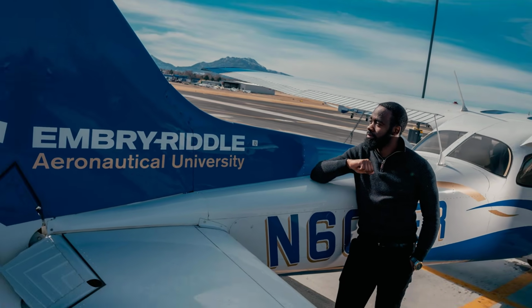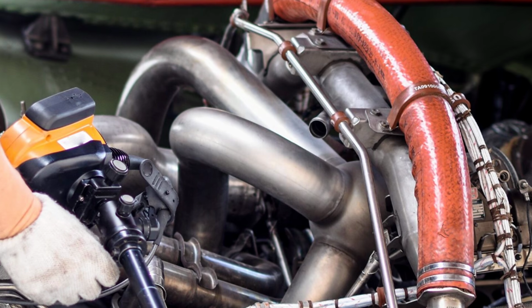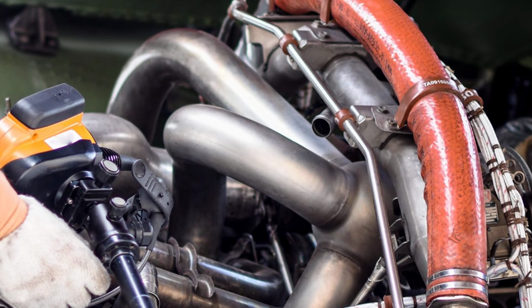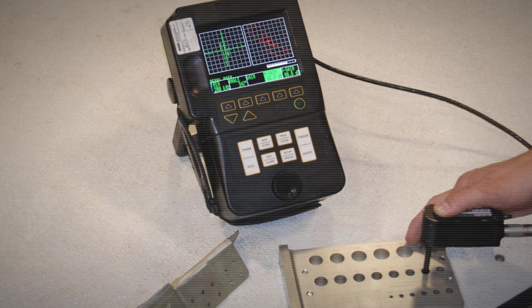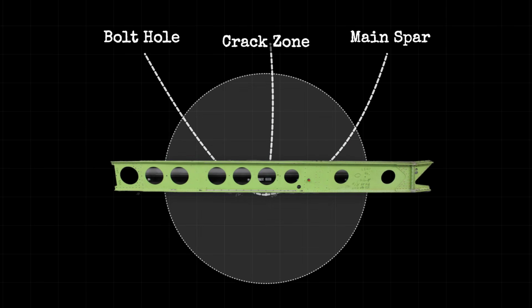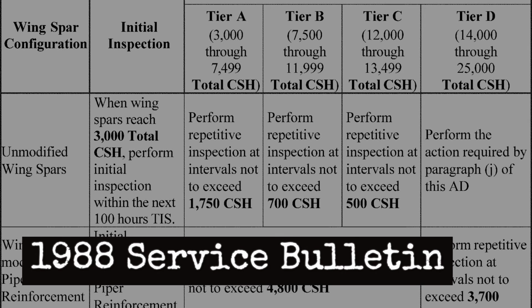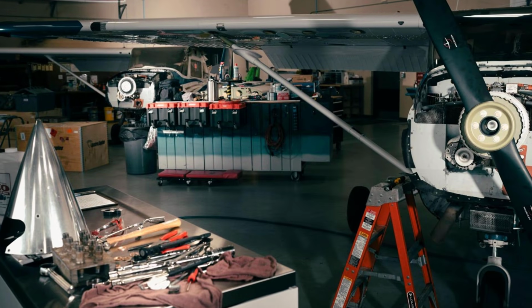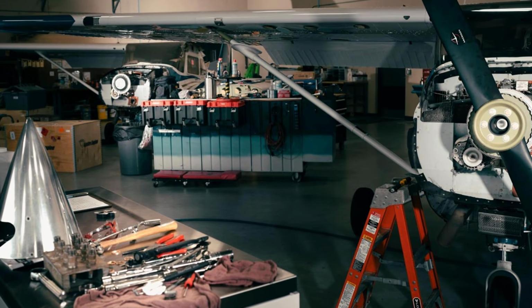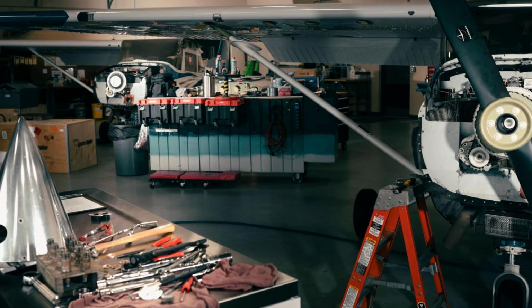A second Embry-Riddle Arrow in the same fleet was immediately inspected and also found to have cracks. The only method capable of detecting these cracks before they reached critical size was a high-frequency eddy current bolt hole inspection. Piper's 1988 service bulletin threshold would not have applied to the 2018 accident aircraft for another 23,000 flight hours.